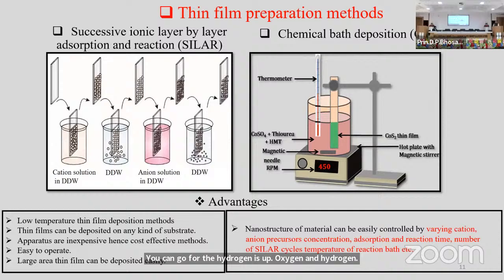So what we do, we put the materials, the copper, the cobalt sulfate and thiourea. Now these are quite cheap materials, easily available. Put them together and put your substrate inside, and just heat it sometimes, or even do it at room temperature.